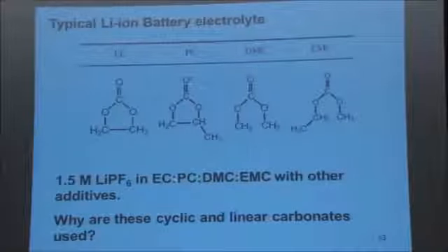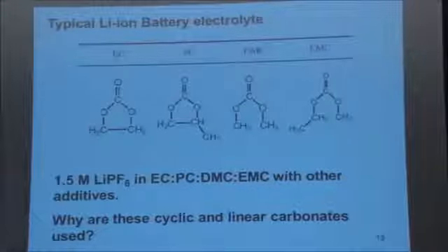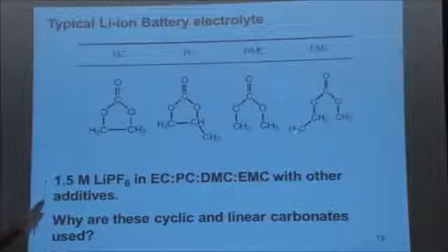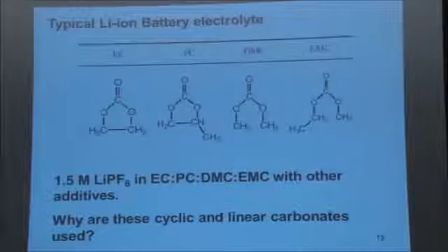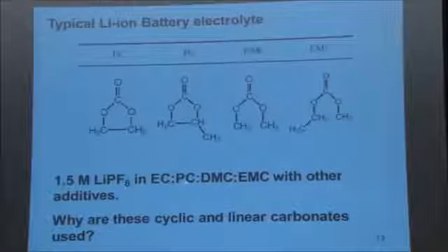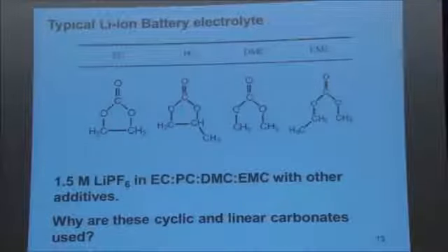Okay, so we got to know a little bit about the electrolyte in these batteries. They're typically organic carbonates like ethylene carbonate, propylene carbonate, dimethyl carbonate, ethyl methyl carbonate. A typical battery electrolyte might be lithium hexafluorophosphate dissolved in a mixture of these solvents. The solvents are mixed because some of them have much lower boiling points and give good low temperature performance. Some of them form very good passivating layers on the negative electrode. So using a mixture tends to have benefits.